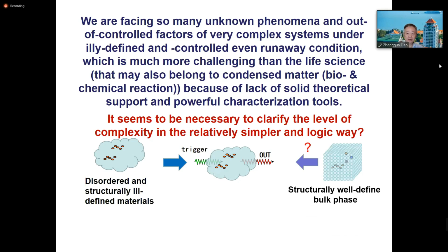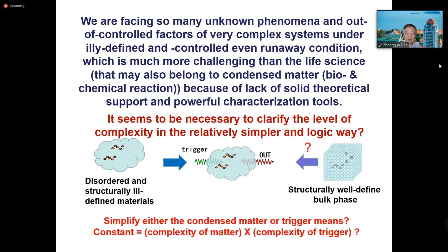So, in my opinion, there are two approaches. One is to have a relatively easy sample prepared and have a good trigger process, or we have some structurally well-defined sample. Then we can create something that is possibly relatively under control. Then we make a triggering. So we possibly need to simplify either this part or this trigger part. If we have too complicated a mixture, then this constant would be very, very high. But we need to have a small constant, so it's to reduce one of the complexities if possible.